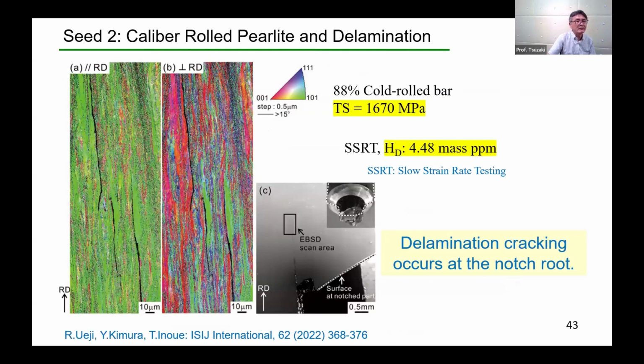What I think is important about their result is this. Delamination cracking occurs at the notch root, as shown here in C. Please look at the EBSD inverse pole figures in A and B, where delamination cracks propagate along the pearlite block boundary, namely the boundaries between the red and blue region shown in B. This delamination should be reducing the stress concentration at the notch root, which is good for hydrogen embrittlement resistance.